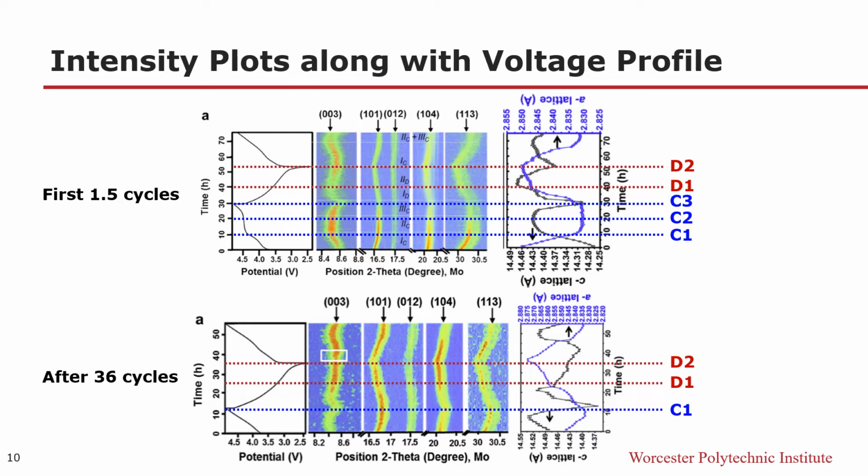In this voltage region, lithium ions are extracted from the lithium layers since the energy required to remove lithium ions from the lithium layers is less than the energy required to remove them from the transition metal layers. The extraction of lithium ions from the lithium layer increases the electrostatic repulsion between the oxygen layers, which causes unit cell expansion along the c axis.